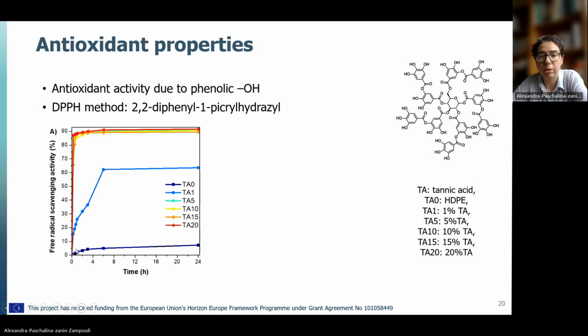Here at the bottom of the graph, we have neat high density polyethylene, which has a negligible scavenging activity. Here you can see the composite with 1% of tannic acid, which is already showing good antioxidant activity. And here are all the other ones.